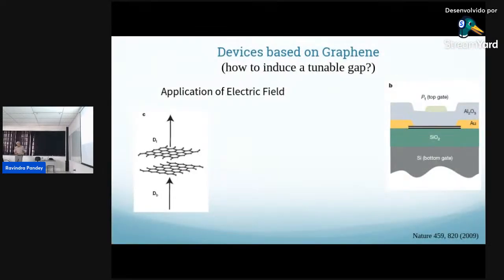Again, this is an experimental paper back in 2009. What they said is, let's take the graphene bilayer and apply an electric field. You can see here, because of the distance, the carbon atom in the lower layer is going to experience a different electric field compared to the upper layer because they are separated. This difference in electric field induces an inhomogeneity in the carbon atoms. This inhomogeneity basically gives you the gap. That's the physics behind it.